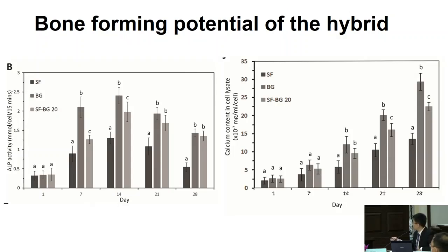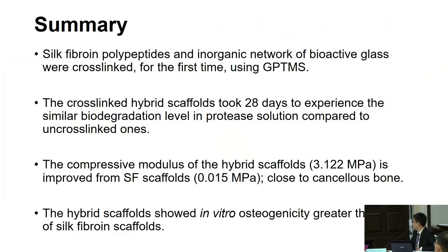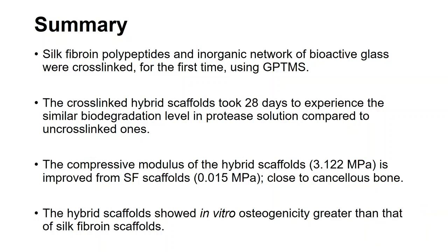And also, we tested for the early marker for osteogenesis and the late marker. And we found that our hybrid scaffold has better osteogenic property compared to the silk fibroin. So this means that the hybrid scaffold showed in vitro osteogenicity greater than that of the silk fibroin scaffold.